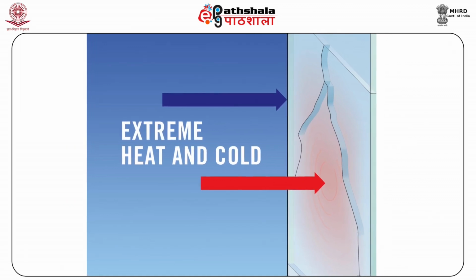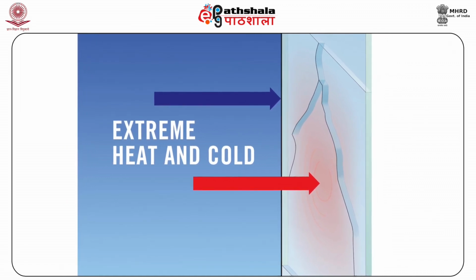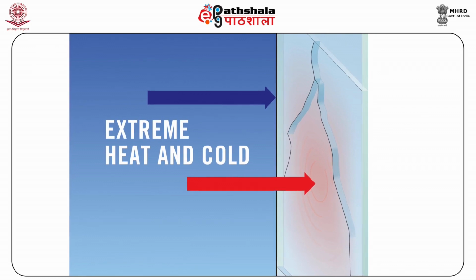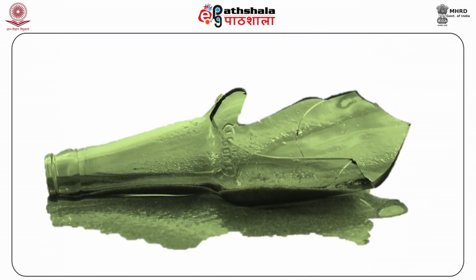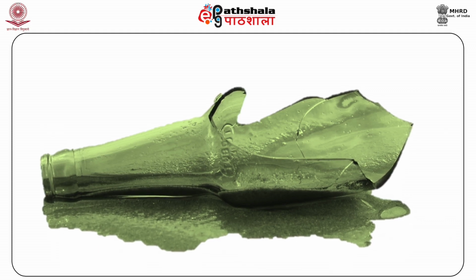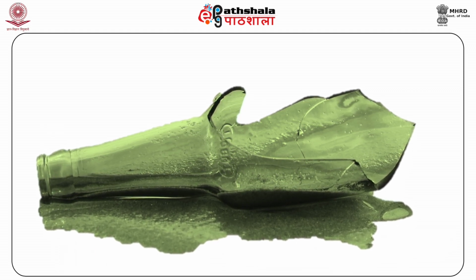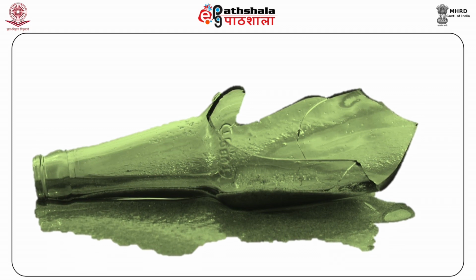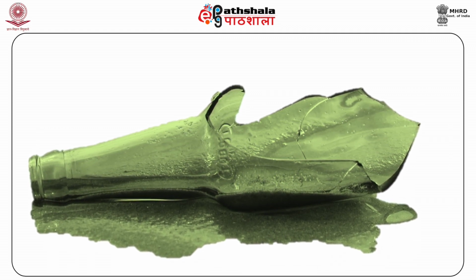It usually originates at the heel or bottom where stresses are greater. These rarely originate in the neck of the bottle, as the neck is stronger than the sidewall.